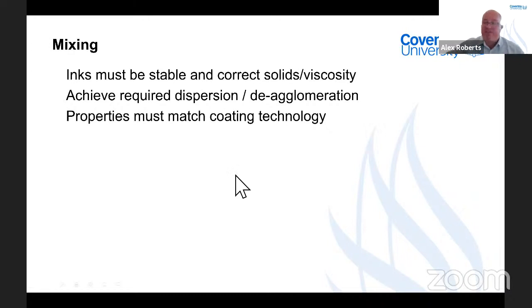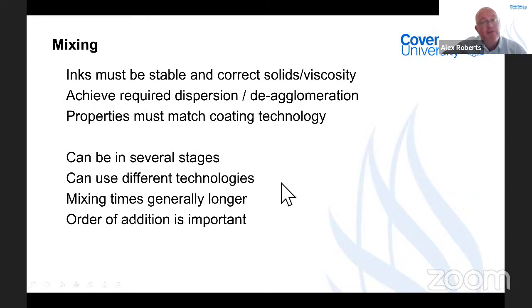We must achieve the required dispersion and deagglomeration of all of the particles. We must go through this mixing process and make sure everything is where it needs to be so it can set in the electrode. Now, as you find going through these processes, it can be in several stages, and you may need to use more than one technology to go through. A good example of this is carbon black. And I'll refer to the carbon black several times through the presentation.